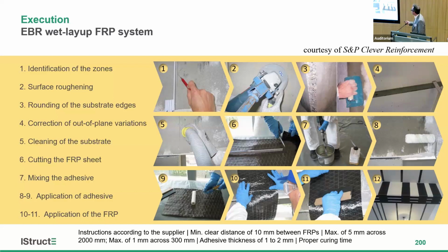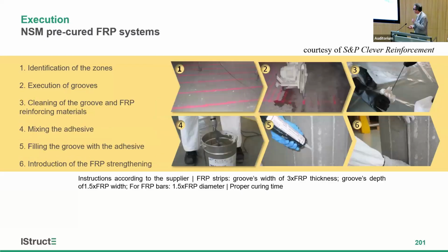Then again, you have to verify out-of-plane variations, clean the sections, cut the FRP sheets according to the design details, prepare the adhesive, apply the adhesive on the surface to be strengthened, saturate also the FRP sheets, and then apply the FRP sheets, removing the excess adhesive. If we need to apply more than one layer, then we have to repeat this process until we comply with all the requirements detailed in the design drawings. And then here you can see an example of how it looks at the end.